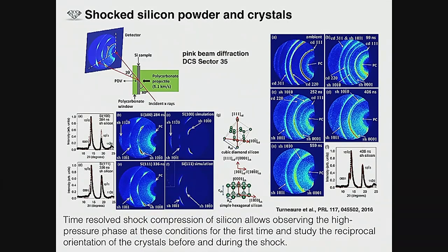That's actually really impressive. They studied both the powders and the single crystals for this material. With the powders, they could see for the first time for sure what are the high pressure phases in these conditions that were obtained. The single crystal data don't look like the single crystal data that you can collect in your home laboratories, right? 500 peaks, very sharp peaks, etc. But they are extremely significant, and they use this data. The scope of this work is really to look at how deformation happens. First of all, the question will be, if you shock a single crystal, what do you obtain in terms of texture? Do you obtain another single crystal? That would happen to be the case. How does the transformation occur? What is the orientation of the crystal before and after shock?